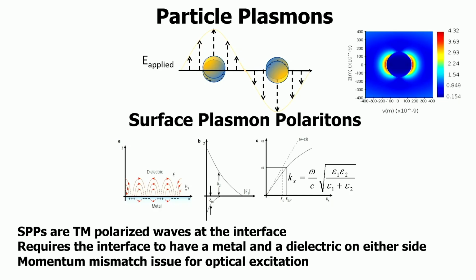Similarly, if we have a metal and a dielectric interface, we can excite a charge density wave, which propagates along the interface. It has a certain dispersion profile, which shows that just by shining light on an interface, we cannot excite this charge density wave because of the momentum mismatch. For a given photon energy, the surface plasmon polaritons cannot be excited, as the momentum matching is not satisfied.